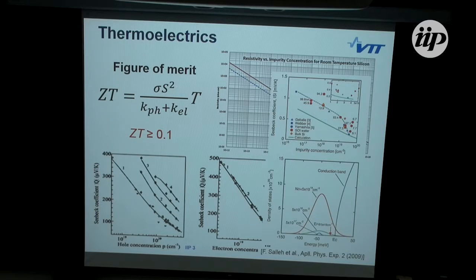And as shown by Davide, when these are optimized, one can get quite a high figure of merit out of these membranes. The trick here is really that one can increase it without affecting too much of the electrical properties. One can go very high in the doping density, and the thermal conductivity can still be separately reduced by going to thin films.